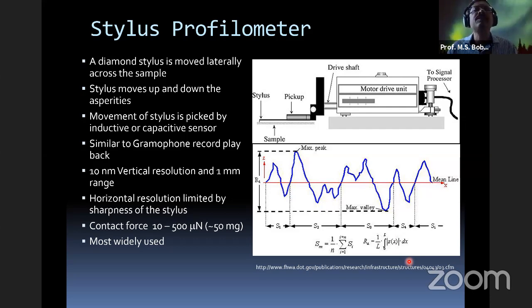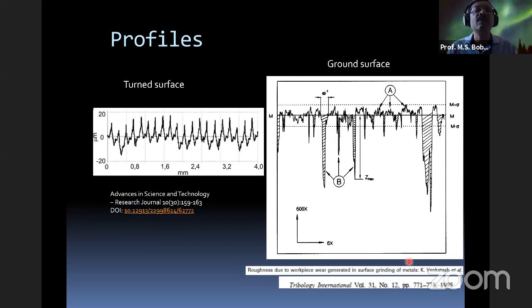And once we get this profile, we can see how the profile is varying. You see, this is a turned surface profile of a typically turned surface. And these peaks correspond to the pitch, that corresponds to the feed rate of the tool with which we have been cutting. We all know that feed rate has to be very small if you want to create a smooth surface, and depth of cut has to be small. And this is a function of depth of cut and the shape of the cutting tool, your turning tool, nose radius especially, and the feed rate decides the roughness.